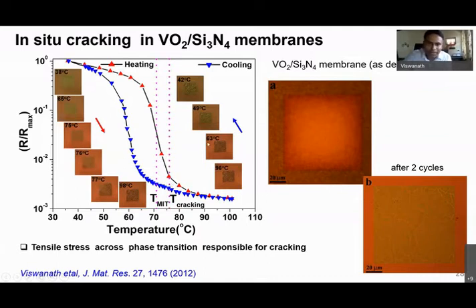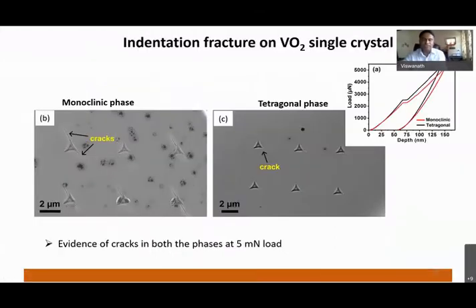you can see the cracking pattern; optical images I have also embedded here. It started showing cracks. Within 2 cycles, we can see the entire membrane is completely fractured. So the fracture can happen during the phase transformation itself. People have also shown, when they try to grow epitaxial VO2 beyond about 10 nanometers of critical thickness, the epitaxial thin films also undergo cracking.